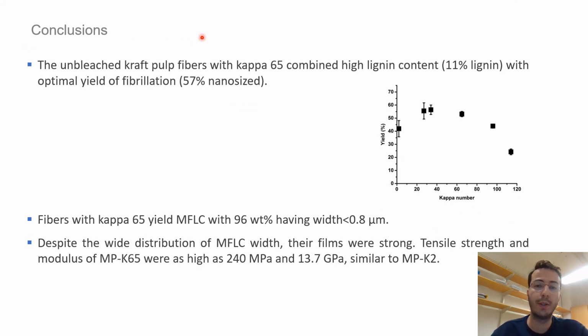So by this, I would like to conclude that the Kraft pulp fibers with kappa 65 combined quite high lignin content, about 11% lignin, with optimal yield of fibrillation, about 57% nano-sized fibrils, which is quite high compared to the rest of samples, as you can see here. And these pulp fibers with kappa 65 actually yielded MFLC, which comprised about 96% of fibrils with the widths less than 0.8 micrometer. And the films from these MFLC, despite the wide range of microfibrils and large microfibrils, are mechanically strong and comparable with the nano-sized fibril films from the literature.